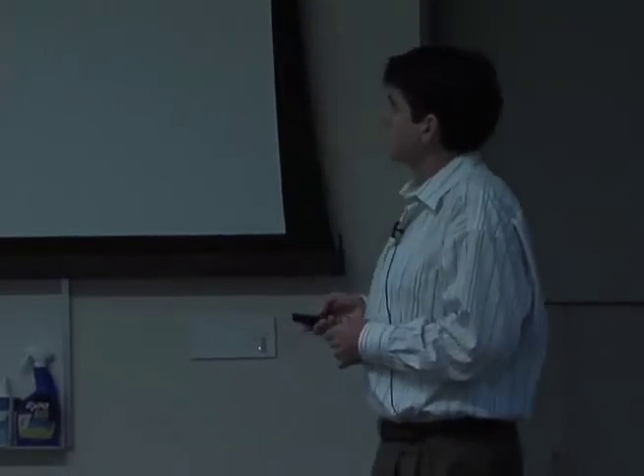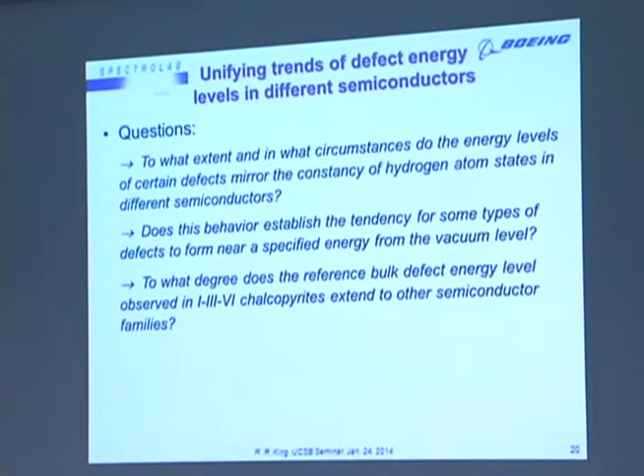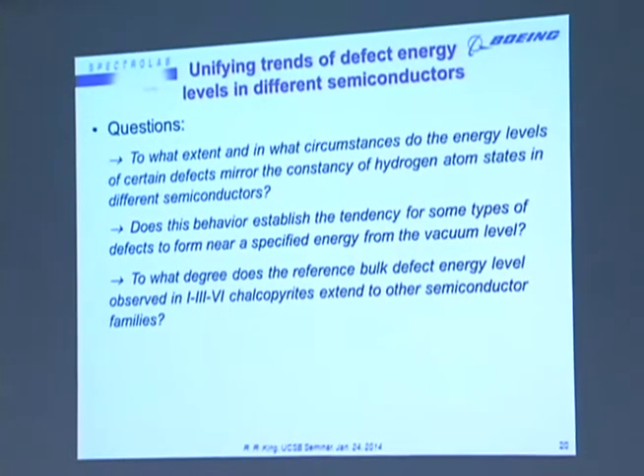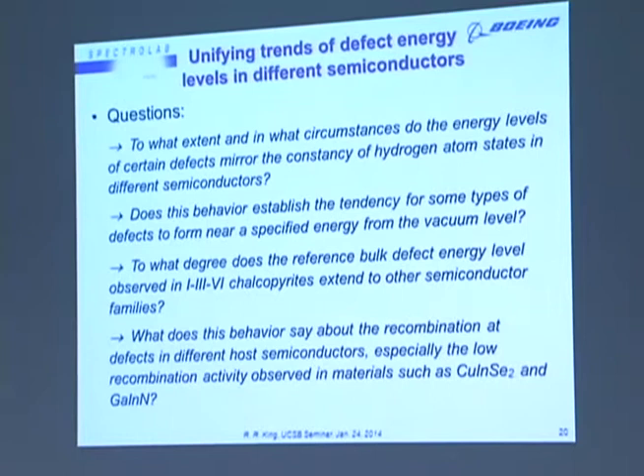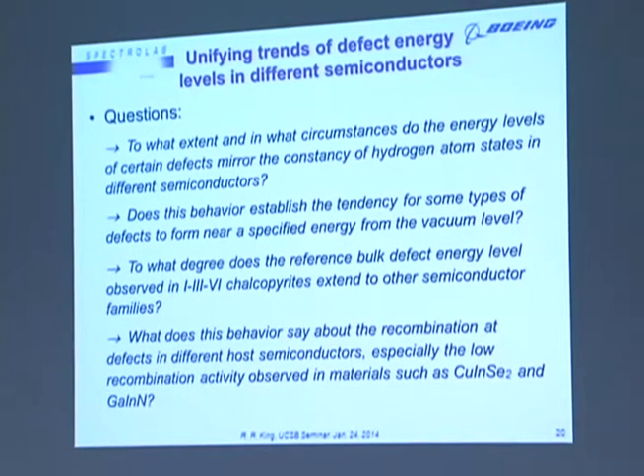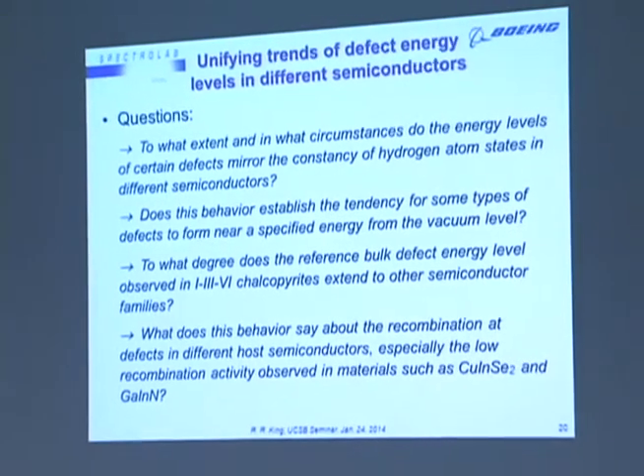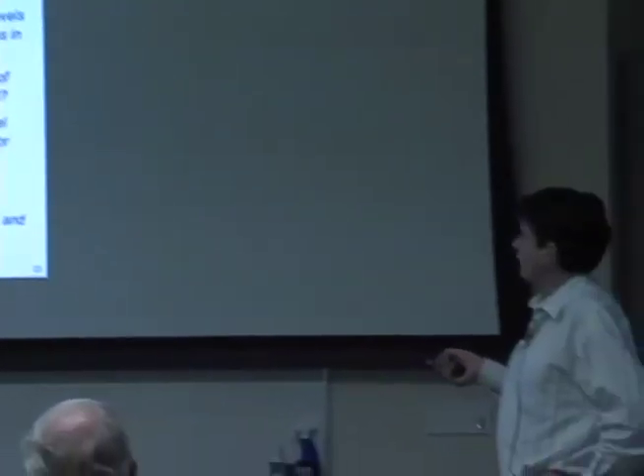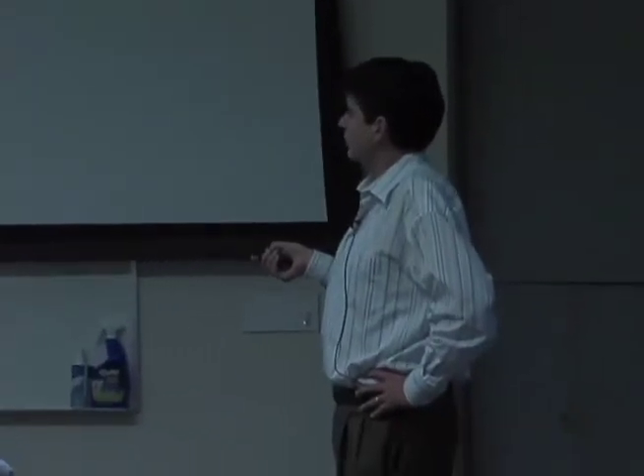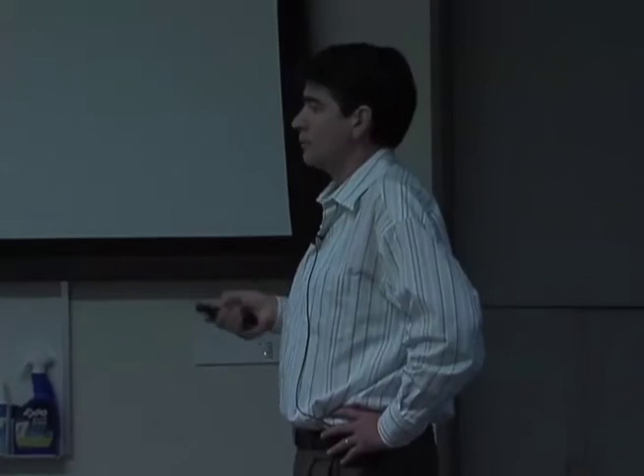So to add to our list of questions, to what degree does the reference bulk defect energy level observed in I-III-VI chalcopyrites extend to other semiconductor families? And what does this behavior say about the recombination at defects in different host semiconductors? Of particular interest is the very low recombination activity that's observed in materials such as copper indium diselenide and gallium indium nitride. Copper indium diselenide has extended defects that are nearly benign in terms of their recombination activity, which is very intriguing and of course would be very desirable to replicate in other new semiconductors.